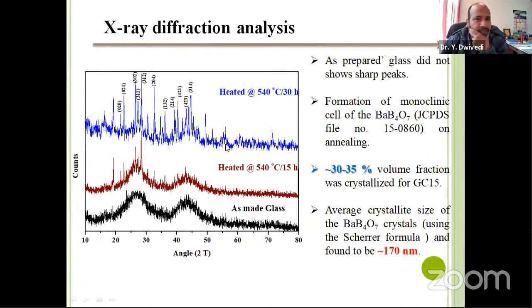For the X-ray diffraction analysis, this is the as-made glass, the characteristic feature of borate glass you can see here. When you heat it for 15 hours, you can see some spikes. Those spikes represent the formation of crystals in the lattice.